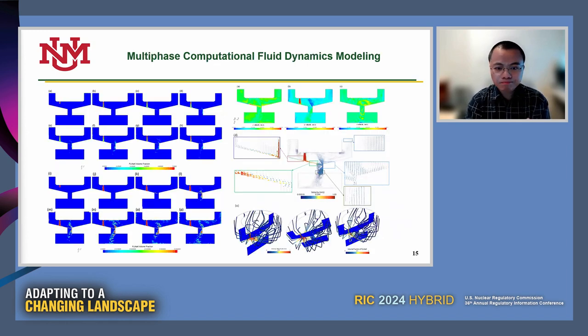Okay, next slide. As I just mentioned, more results are shown in this one. The top left figures show the fluoride salt volume fraction from 0 to 1, and we can only see the bulk effect. In the initial step, you can see a little bit of salt going from the hole, and then salt impinging on the catch pan. Going down to the last two steps, you can see the salt go along the catch pan, impinging on the drain hole, and causing some splashing there, which will potentially lead to more salt aerosol generation in that region.